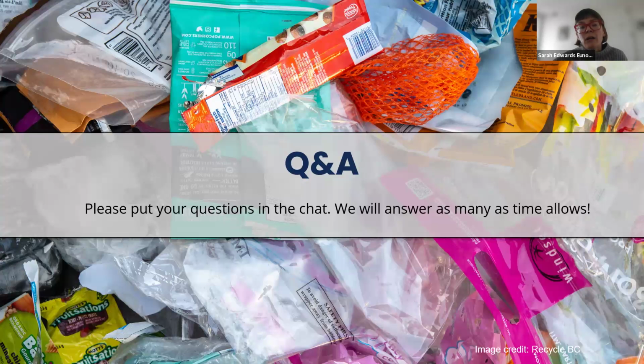And then we can look to some of the research and work that's been done in Europe. FOST Plus, which is the PRO for Belgium, has made quite significant infrastructure investments to try and capture this material through its curbside services. They have a collection service based just on collecting containers and films, so the glass and the fiber are outside. They effectively have a 3-stream or 4-stream system, so they're better able to manage those materials as a mixed stream. But even there, they're struggling to find specific end markets at the moment, though at least the collection is taking place, and they do have some end markets.